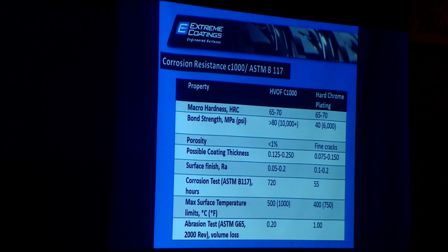Some of the tests which are available in the market, you can Google this also. The first test is for corrosion resistance. The test name is ASTM B117, where you have a piece which is tungsten carbide coated with HVOF, the process which we did, and on the other hand a piece which had hard chrome plating, and we submerged them into the particular solution. Now when you compare, the micro hardness of the coating is almost similar to other solutions, but our bond strength is very high. The porosity is less than 1%, but hard chrome plating always has fine cracks.